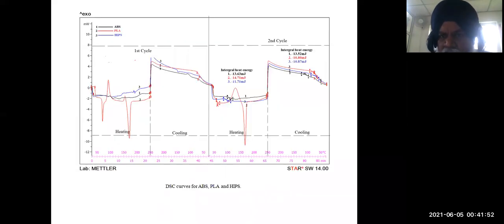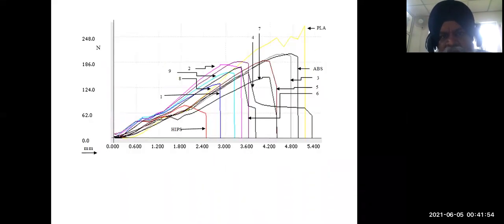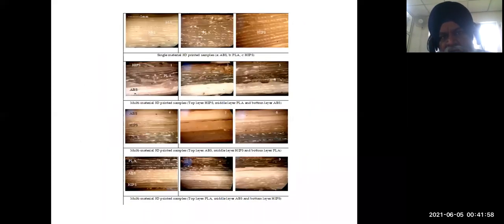Of course, the thermal stability we also did, like in the previous case. And then we developed the stress strain curve. And using this, we also tried to see their microstructure. Now you see here in this case, this is a single composite material of ABS. So I can clearly see the staircase effect in the 3D printing, which is also commonly seen in PLA as well as in HIPS. But once I have a lower layer of ABS, then I put a layer of PLA over it. What I am observing, some globules of PLA are spilling out.